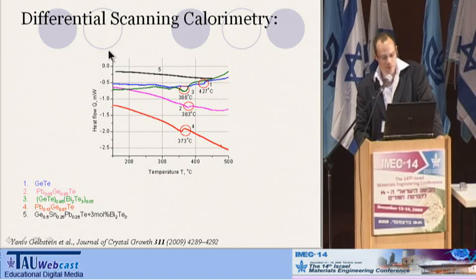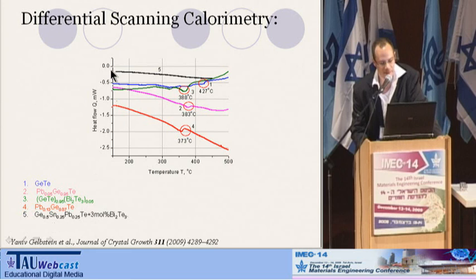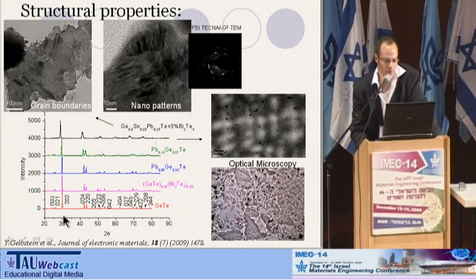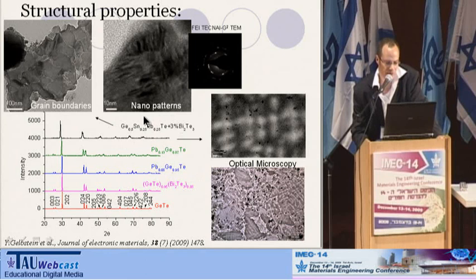While further investigating germanium telluride and lead germanium telluride-based alloys, we used DSC to evaluate precise phase transition temperatures for each composition. We found that for germanium-tin-lead telluride — by also introducing tin into the system — there is no such phase transition at all. From the XRD patterns, all compositions except the one containing tin telluride show doublet patterns for the rhombohedral phase, but for the composition with tin telluride only a single peak pattern is observed, indicating cubic nature. In addition, introduction of tin telluride resulted in some periodic nano- and microstructures that we could not explain at first.